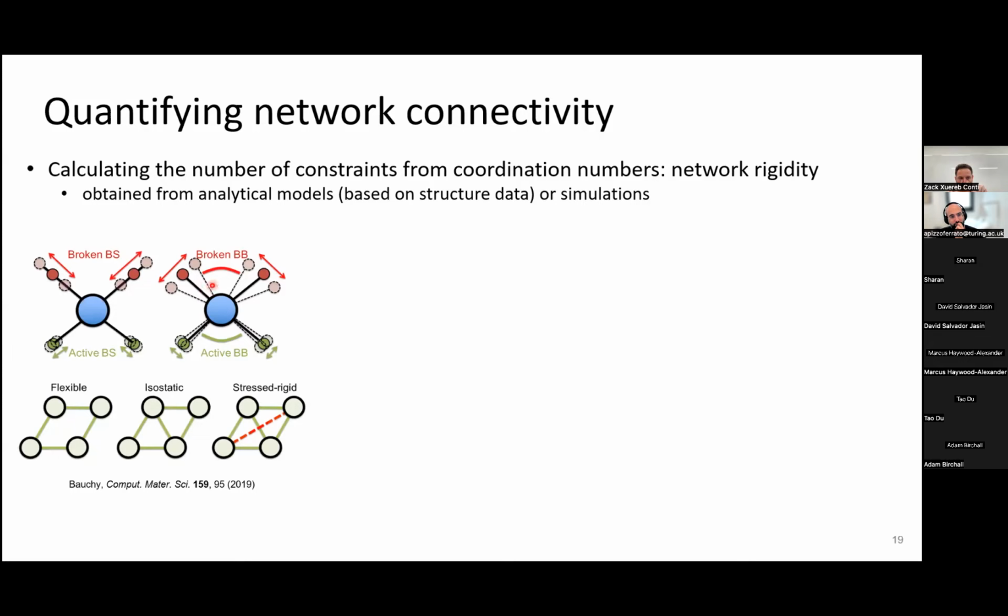So here are some examples of what we've been doing. Coming from the structure that I just showed you, we can calculate different things. We can calculate how rigid some of these bonds are, both in terms of what we call radial constraints, so bond stretching here, or angular bond bending like over here. Some of these will have large fluctuations around the mean value, both in terms of bond stretching or bond bending, and others will be much more constrained.